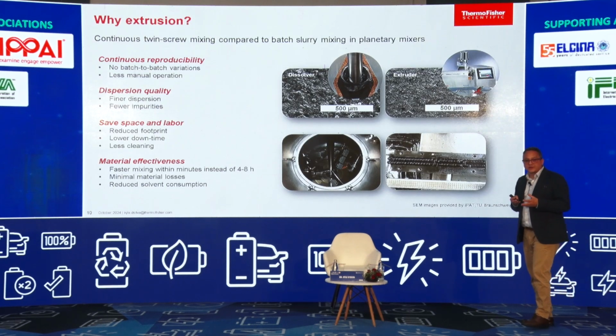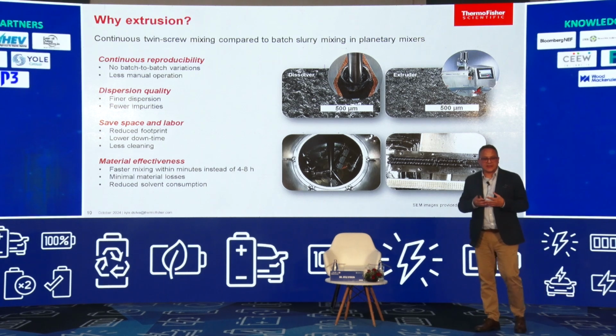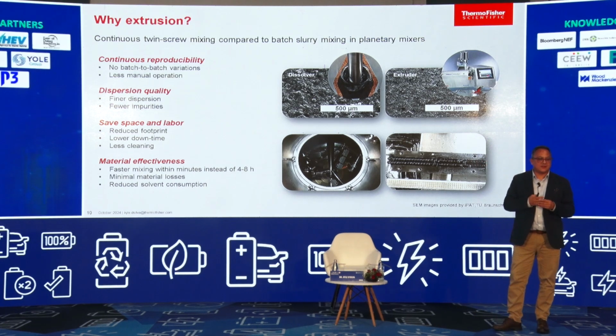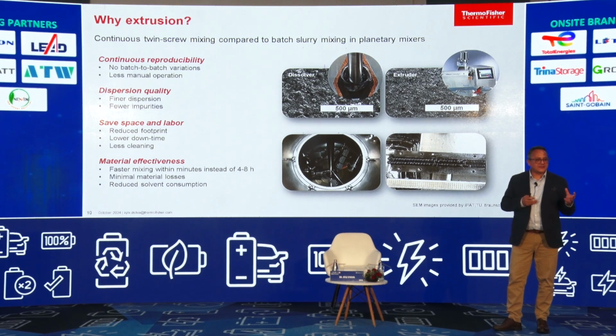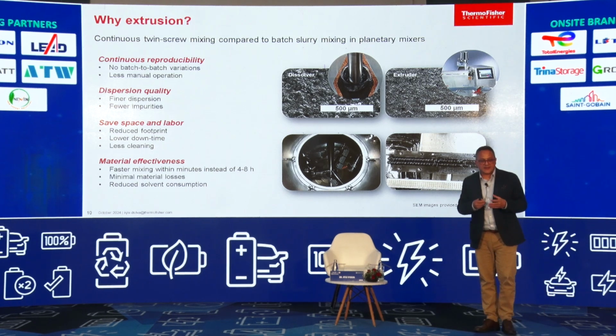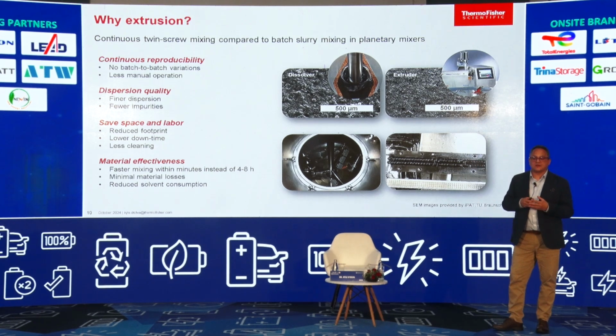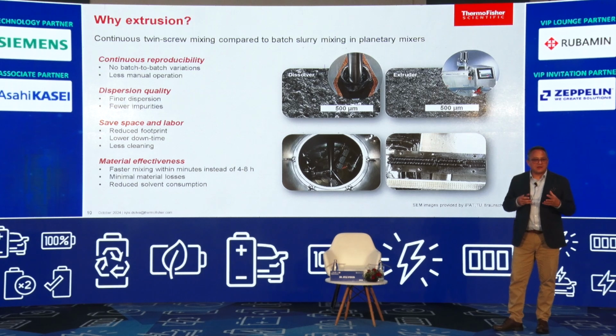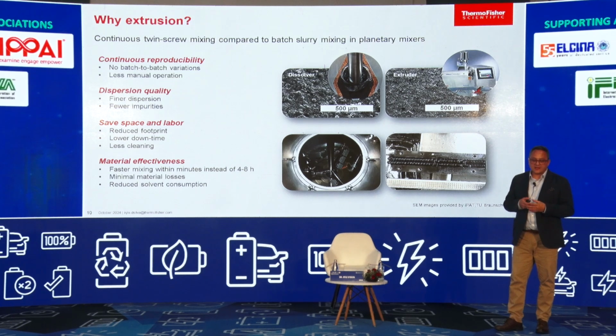So why use extrusion? Well, extrusion gives continuous capabilities in your mixing process. So you don't have as many batch-to-batch variations. You get greater dispersion of the material, fewer agglomerates and aggregates of your particles. So consequently, you have a very fine mixing process. You can also mix powders as well as slurries in the same system. It also allows you to save on time and labor.